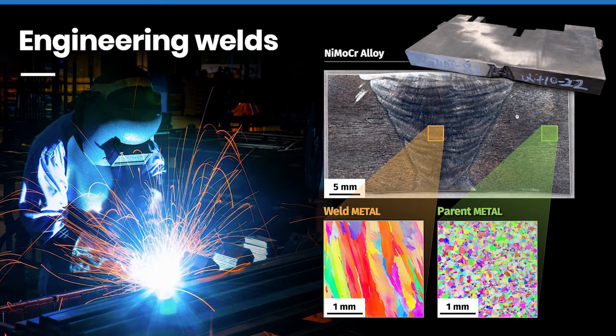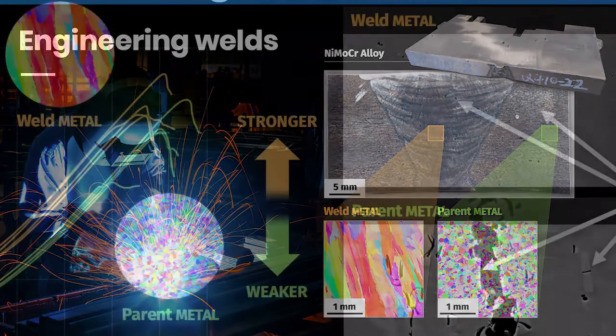And here comes this multi-scale understanding of materials. So even though the weld metal and the parent metal have similar chemical composition, when we look at the microscale, they are significantly different. While the parent metal contains a large number of small crystallites, the weld metal contains significantly larger crystallites. And this has consequences not only on mechanical properties of the parent and the weld metal, but also on the corrosion behavior, as we will see in the following slides.